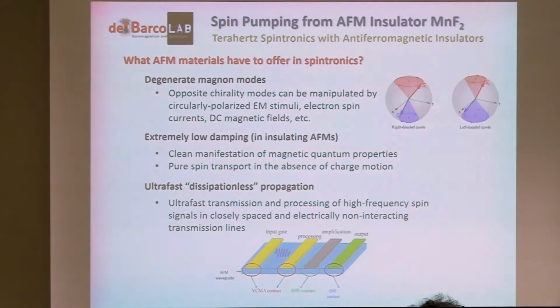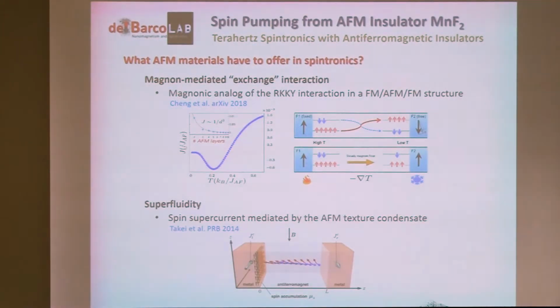In particular, when we're talking about insulating antiferromagnets, those are the ones that I'm interested in. First, nothing moves. There is no charge motion. So dissipation is much smaller. And if you're dealing with a magnetic system where the dissipation is extremely low, you can start thinking about quantum magnetic effects that you wouldn't see in a metallic counterpart, for example. And because of that and some other properties of antiferromagnets, they have been suggested to be perfect materials for dissipationless or quasi-dissipationless propagation of really high frequency magnon signals.